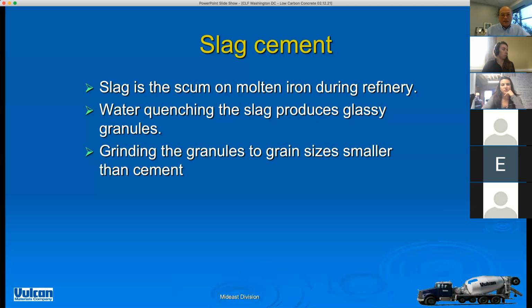Somebody was saying to me that they pour like 10,000 gallons of water per minute on that slag. Rapid quenching produces a glassy material, in the form of very small glassy granules. Then they drain the water off and put it in a grinder, ball mills actually, and grind it into grain sizes that are smaller than Portland cement. So that's what you get, slag cement. Next, please.